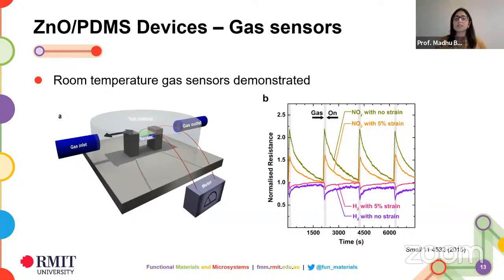So typically gas sensors operate at much more elevated temperatures, but in this case, you can see we can actually get sensing performance of these zinc oxide gas sensors at room temperature itself. So you have a test chamber, and what you're essentially doing is you're monitoring the changes in the resistance in the material as you're exposing it to the gas. So they're conductometric gas sensors. The resistance of the material changes on exposure to the gas.